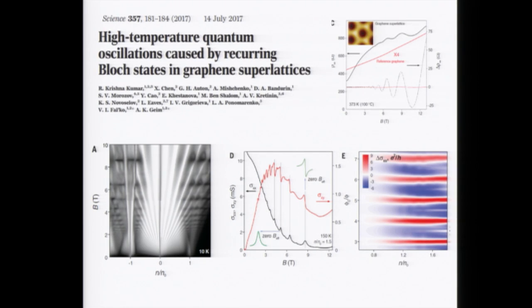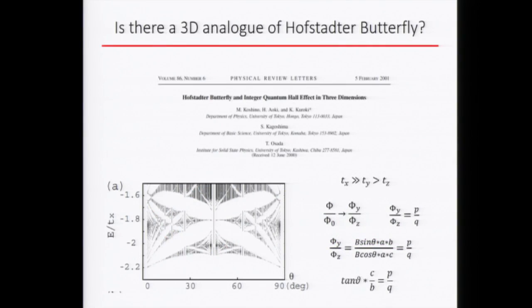The Geim group actually saw an oscillation associated with this effect. The signature is that it only depends on your magnetic field to superlattice flux quantum ratio. It doesn't depend on density. And whenever you reach this commensurate ratio, you have a peak in conductance and also this kind of dispersion-like behavior in your Hall conductance. So what does this have to do with our system? This is a 2-dimensional system, and the magnetic field is strong enough that you have about 1 flux quantum in your unit cell. So actually, right.